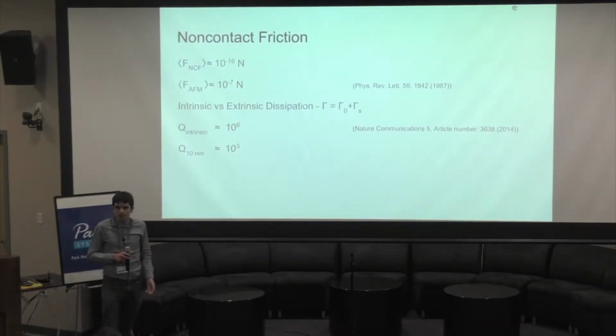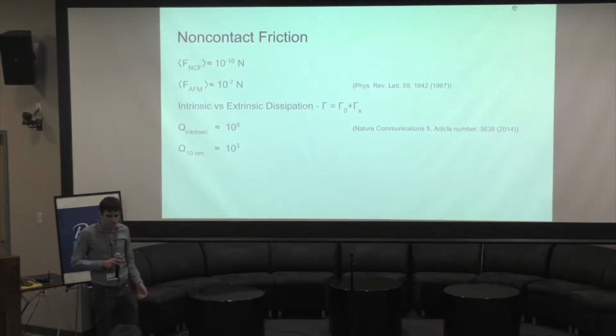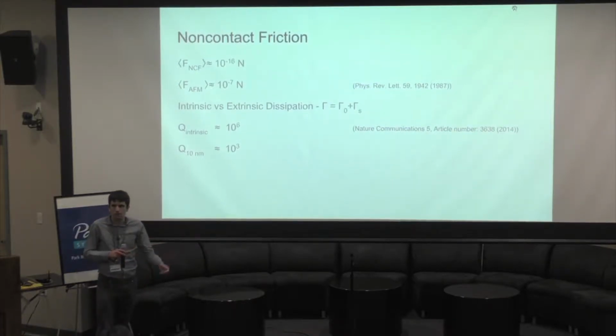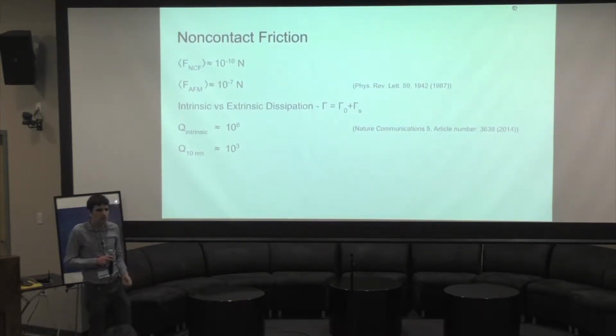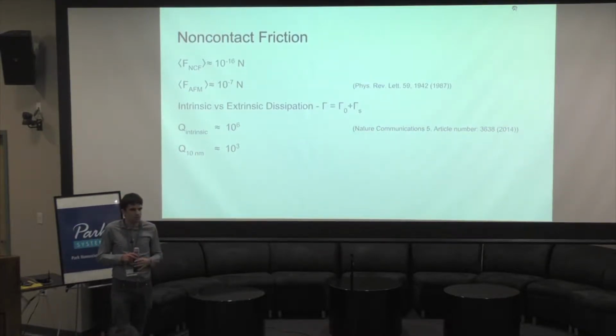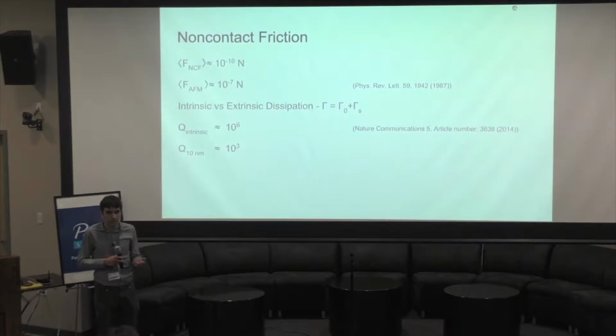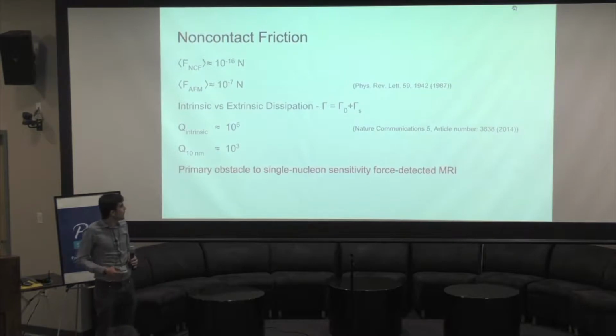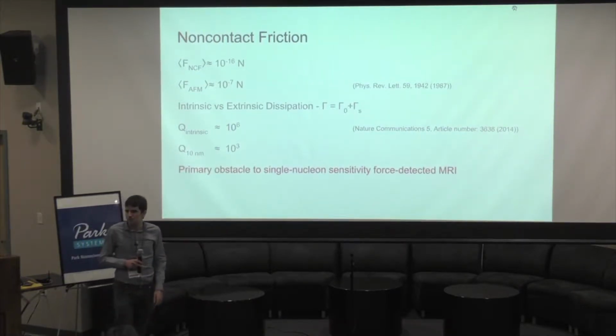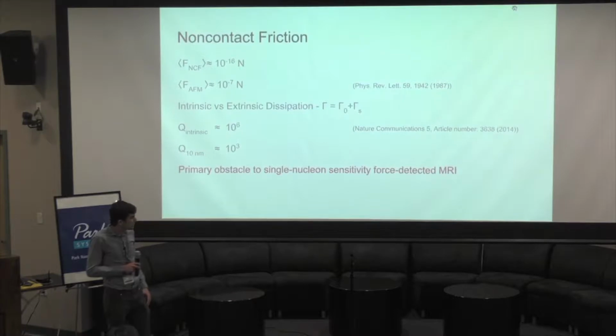The intrinsic quality factor of the best scanning resonators available now, like the nano-ladder resonators that Ye was talking about earlier, is about 10 to the 6. But if you bring them 10 nanometers away from a surface, like you have to do to get high spatial resolution and high sensitivity to magnetic forces in magnetic resonance force microscopy, the quality factor drops off to about 10 to the 3rd. In fact, non-contact friction is the primary obstacle to single nucleon sensitivity force-detected magnetic resonance imaging, which would be a really cool thing to be able to do.